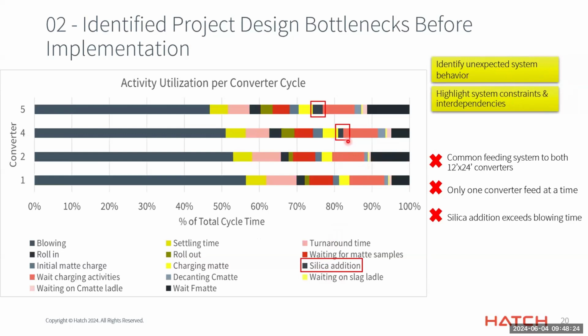So through investigations of the results, we found that there was a design flaw in a common converter flux and revert feeding system to the new converters, where only one material type and one converter could be fed at a time. So this meant that when you had both new converters operating at the same time and both blowing, one has to wait for the other to complete the feeding process, which causes silica feeding to exceed the blowing time. So the results prompted the team to redesign this feeding system before project implementation, thereby improving our throughput by 2%.